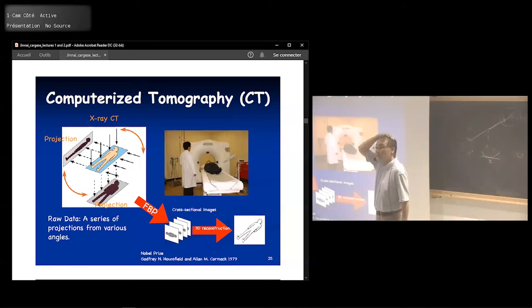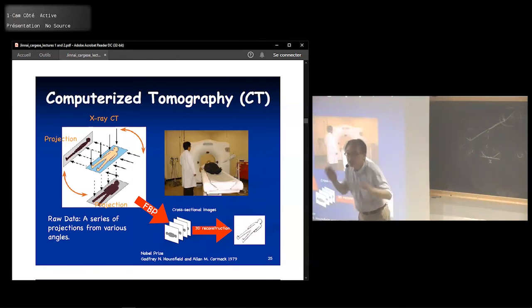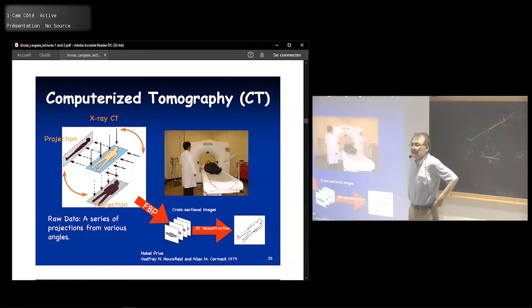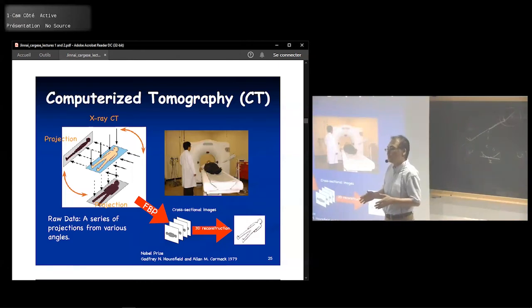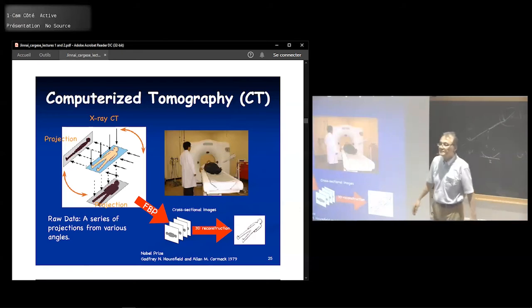For someone who does polymers, but on a much bigger scale, how do you prepare samples that are that thin? How do you prepare samples that are like 100 nanometers thin, and does it not affect, I'm assuming, if you change the preparation method. Still, you can use ultramicrotoming. You can still use the same technique. And for this instrument, you can set up the target thickness, like 70 nanometers, or 150 nanometers or 200 nanometers. So the same procedure. Okay.